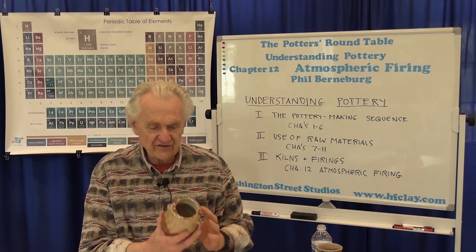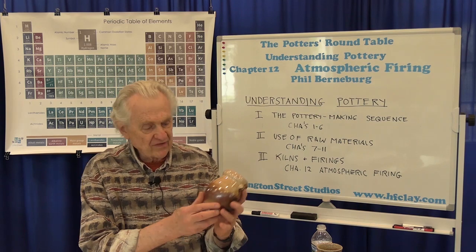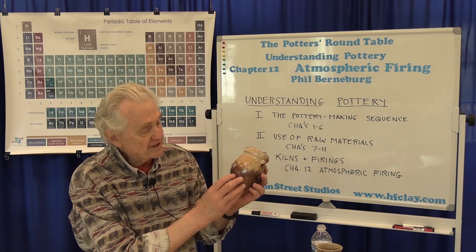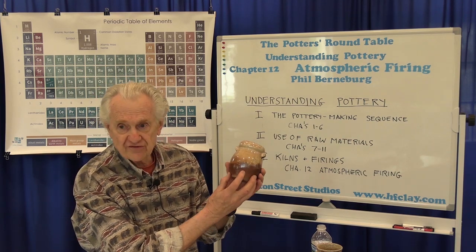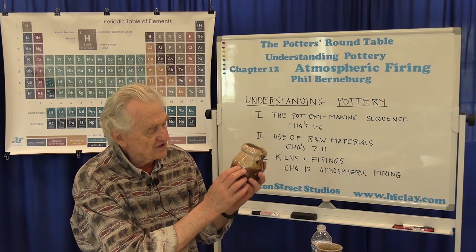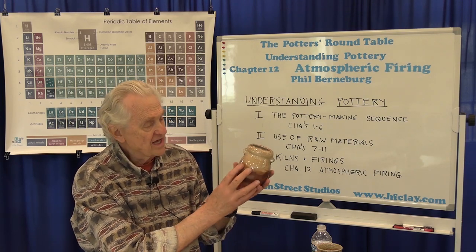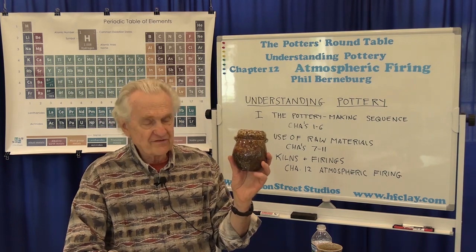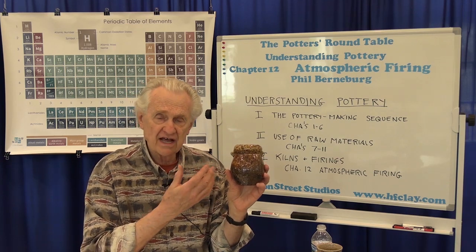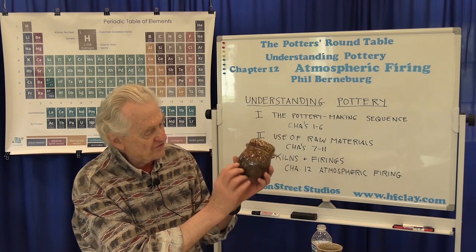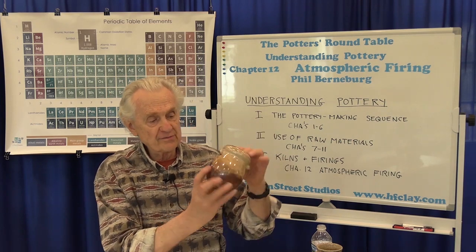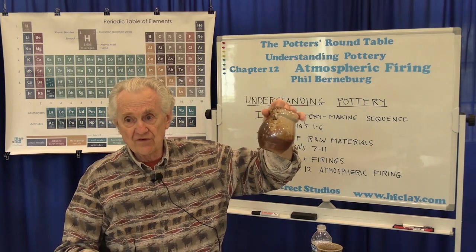This is a good example of a wood-fired pot because it contains a lot of the different things that can happen. On this side of the pot, it's just a little gray stoneware — the color of the clay by itself would just be gray. Down here below this line, this is more just the flashing produced — there's no glaze here. Above that, there was a shino glaze, and so there is also some coloration introduced into the shino glaze. And then on this side of the pot, the pot actually received a lot of ash — so the whole surface got splattered with ash, fired at a high enough temperature to actually melt the ash. Where there was no glaze, it produced a glaze; where there was a glaze, it melted and sunk into the glaze. This nicely incorporates all the different effects you can get with wood firing on one pot.